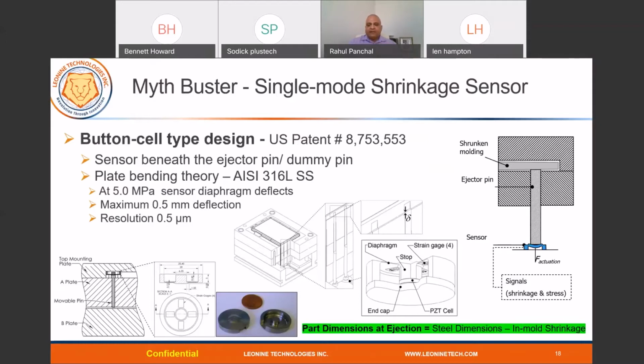And by knowing that in-mold shrinkage, and if you know the steel dimensions, you can calculate the part dimensions at ejection. And you can also measure the pressure using piezoelectric or any other instrumentation. It's simple. But surprisingly, nobody even tried that. The resolution you can get is 0.5 micrometer.